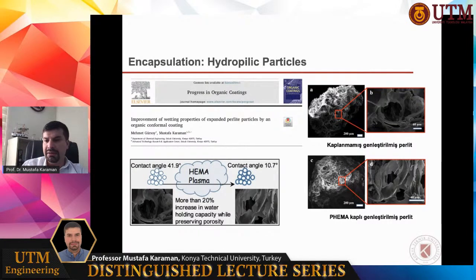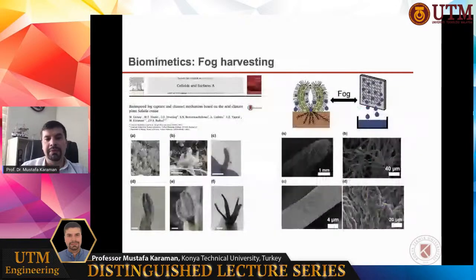The contact angle before the coating was 41.9, and after the coating, the water contact angle value decreased down to 10.7. And the material had more than 20% increase in water holding capacity while preserving the porosity. It preserved the porosity because the technique is highly conformal. The pores of the material are not obstructed with the polymer.